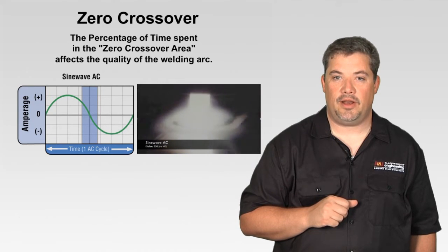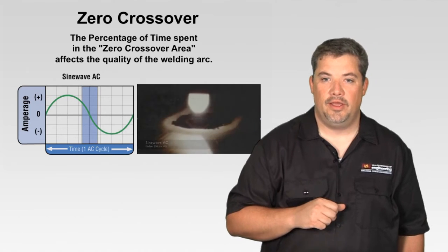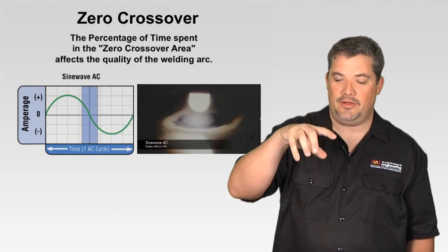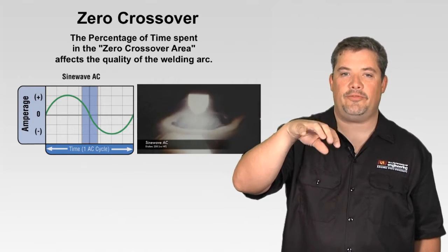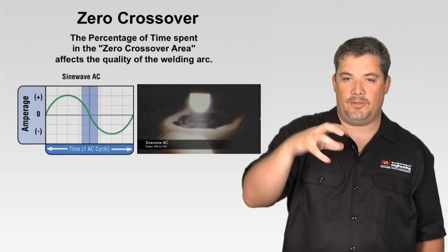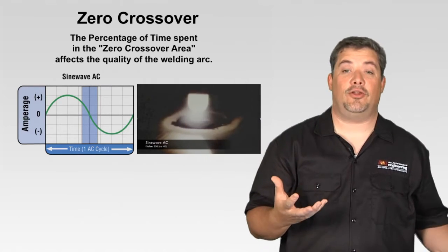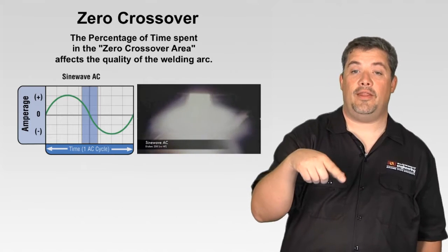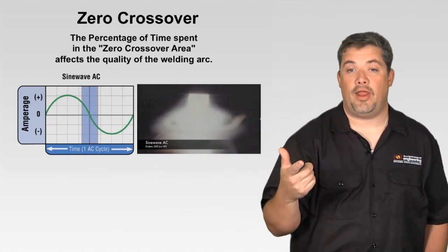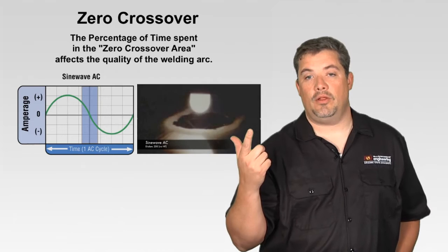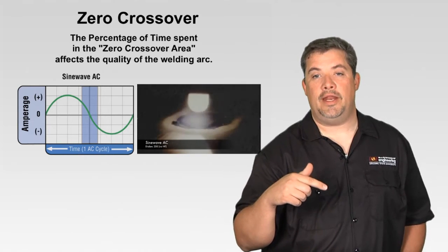There's etching, not etching, etching, not etching. And during that etching zone, you can see the little tiny sparkles happening on the surface of that weld. Those little sparkles are the etching that creates that white zone around the weld. The other half is the actual welding arc heating that part up.